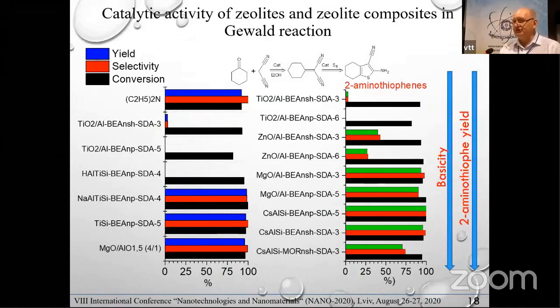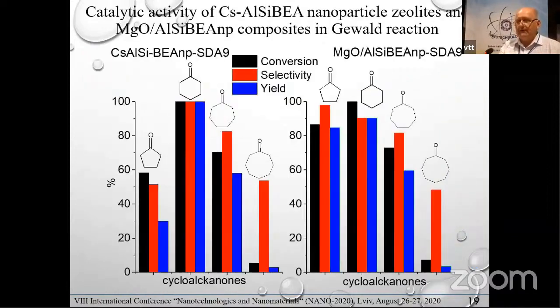We tested different compositions, different materials: magnesium, titanium, or zinc oxide nanocomposites, or cesium or titanium forms of zeolite. And as we can see, very high conversion with very high selectivity can be achieved. For some compositions, the yields of those products can be achieved near 100%. Comparing different substrates for transformation, we can see the highest yields are typical for cyclohexanone or cyclopentanone substrates.